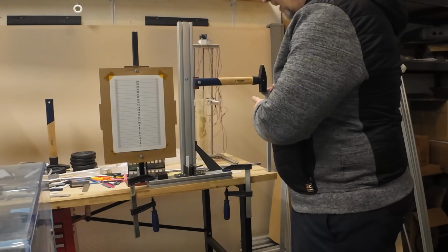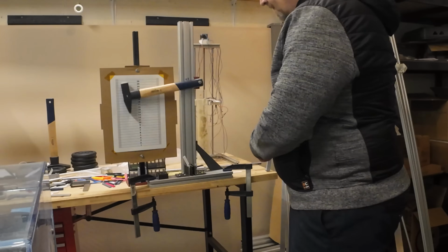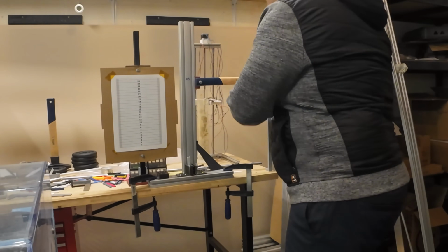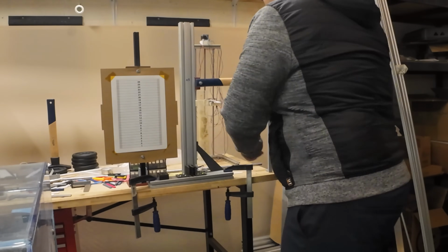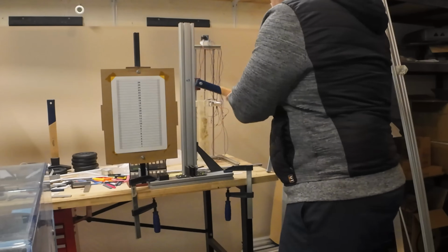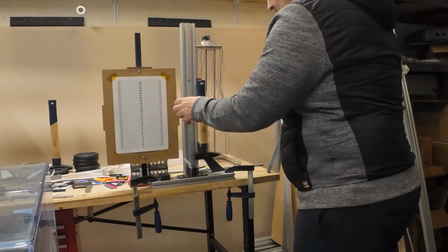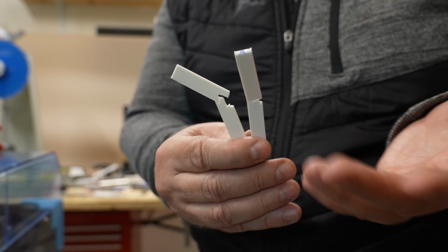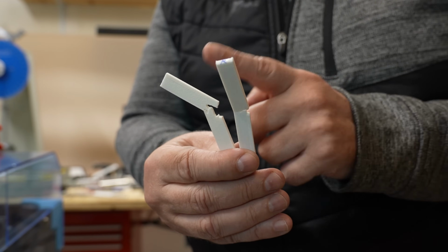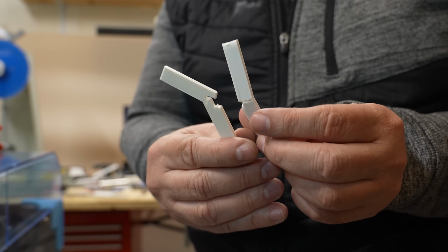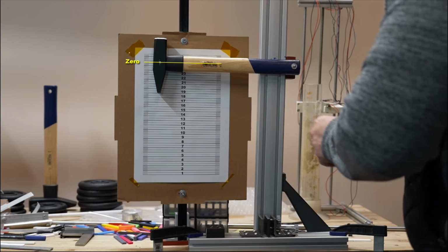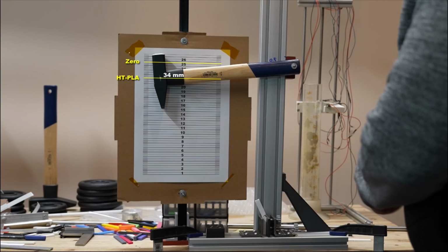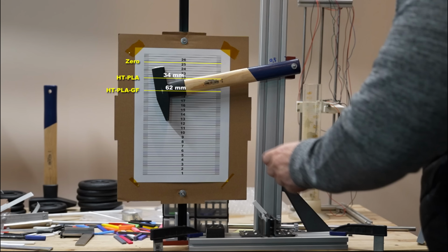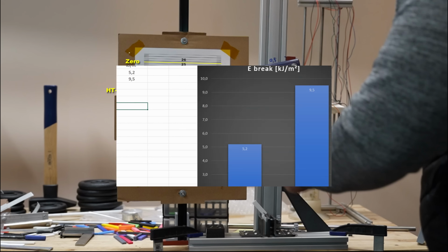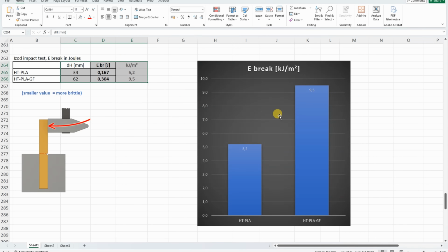Impact test with this half kilogram hammer. This is HT-PLA. Zero position, glass fiber version. Interesting breaks, but actually this was broken when the hammer swung back. Let's analyze the footage. This is the zero position of the hammer, and this is the edge position after breaking HT-PLA, and this is after breaking the glass fiber version. This is not really typical, that the glass fiber version is tougher compared to the non-reinforced version.